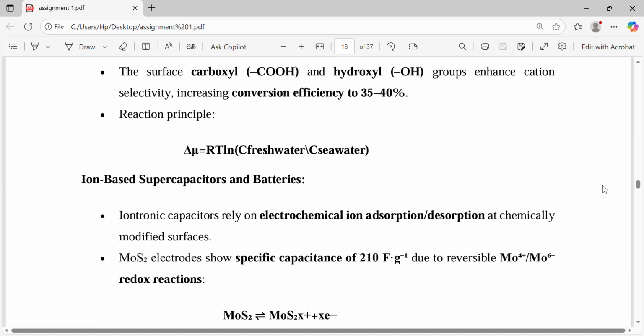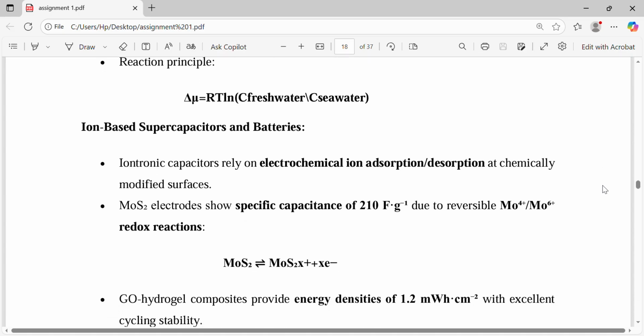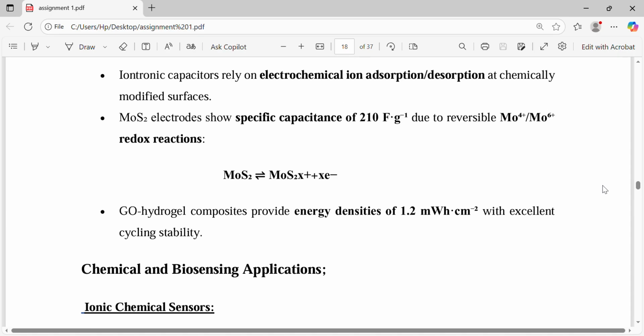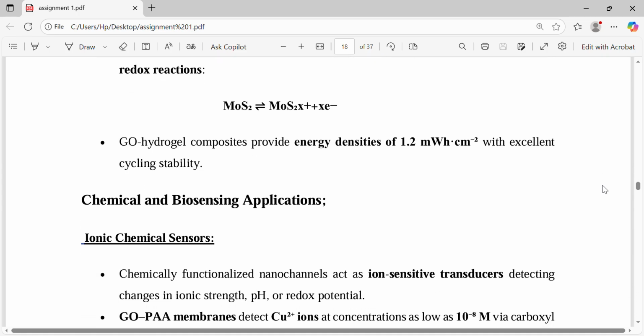Ion-based supercapacitors and batteries. Iontronic capacitors rely on electrochemical ion adsorption and desorption at chemically modified surfaces. MoS2 electrodes show high specific capacitance due to reversible redox reactions. Graphene hydrogel composites provide energy densities of 1.2 with excellent cycling stability.